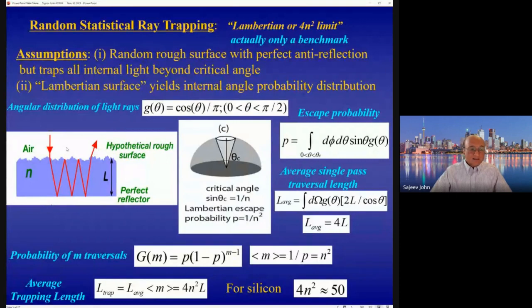So the assumptions behind this simple model are that one has a randomly rough surface with perfect anti-reflection, but it can trap all internal light beyond a certain critical angle, and that the surface has a probability distribution for angular deflection of the light given by the cosine of the angle theta between the normal and the angle to which it's being deflected. So light at nearly 90 degrees has a very small likelihood of being deflected like that, but going straight through is the peak of this distribution.